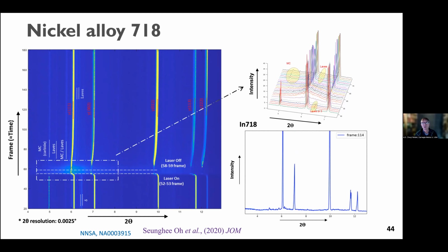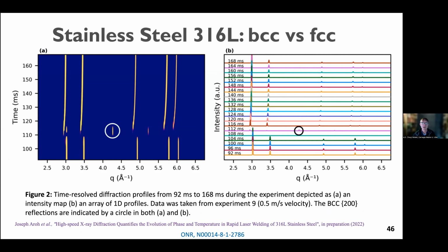One of the reasons to do this at 1ID with its excellent energy resolution is you can see much smaller volume fractions of these second phases, which turns out to be very important in most engineering alloys. You're very often asking questions about fractions down to 1% or even less. So this was already very useful for, in a very accelerated way, illuminating what was really going on in these materials.